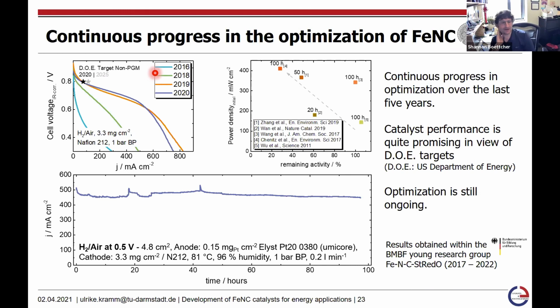So I had some questions about what other characterization people have done on these graphitic iron sites. If you do really long-term testing, have people looked at leaching rates? How tightly is the iron bound in there? Have people done online ICP-MS type experiments? On the practical side, what's going on under those ORR conditions, because it's pretty aggressive, also for the carbon support. And the other thing I wanted to ask about is the nominal oxidation state. Is there any evidence of minority species in your samples that access higher oxidation states under ORR conditions, nominally 3+ or anything like that? Those are the two questions I have.